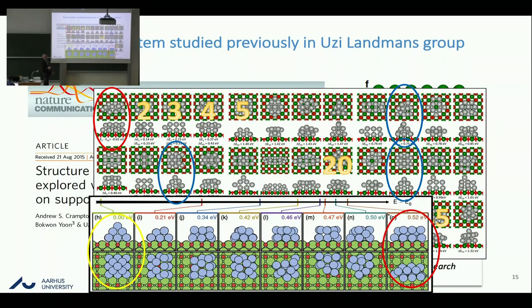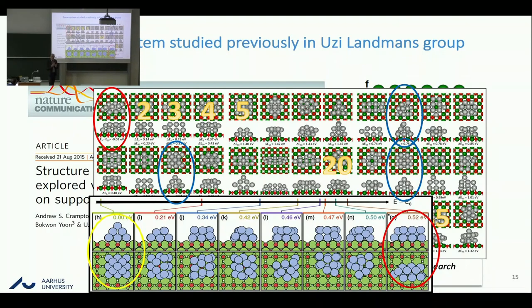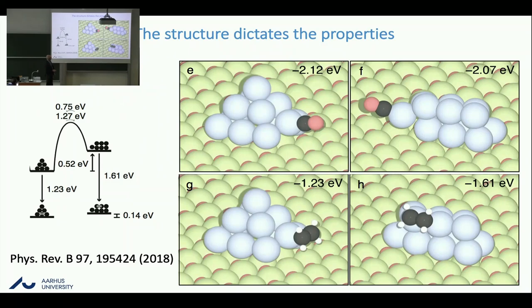I think I've made my point: humans cannot do it. Automated search methods like an evolutionary algorithm can, and even when it goes via a machine learning potential during the search, it can do it. The pyramidal structure is here — that's the hollow one. Up here are other pyramidal-like structures but none of them are hollow. The person who did this work did think about pyramidal shapes but felt it had to be solid because metals are solid. It matters whether you have one model or the other — not for CO, but it matters for ethylene, which binds much stronger on the wrong model.